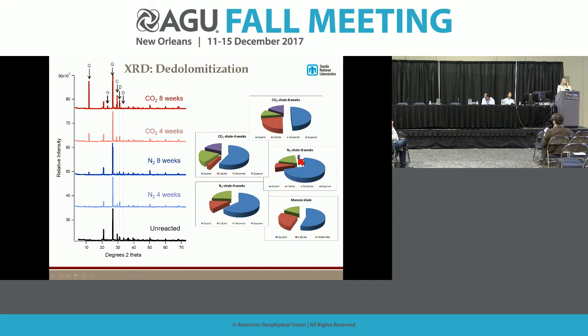But as opposed to the control, in the CO2 pressurized reactor, right? Again, we're starting with a lot of calcite. After 4 weeks, we dissolved almost all the calcite. We have very little, this red slice here, left, and precipitated a lot of gypsum. But if we let the system go longer, for 8 weeks, we precipitated calcite back. And in fact, at the end of the reaction, we have more calcite than we started with.